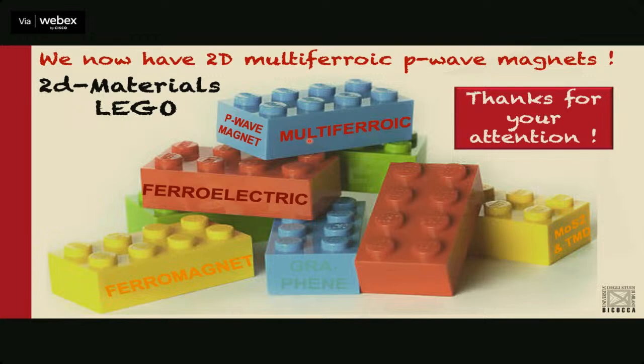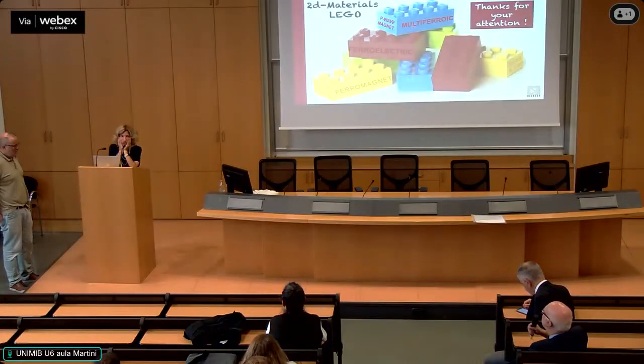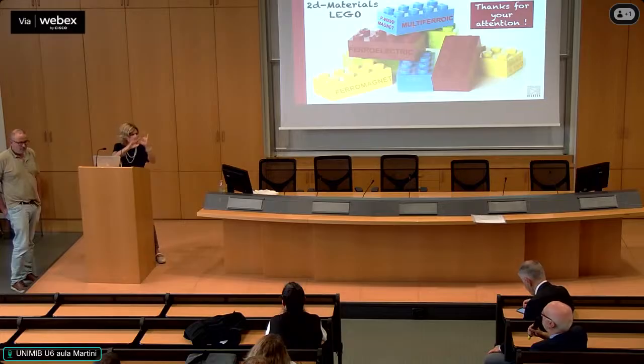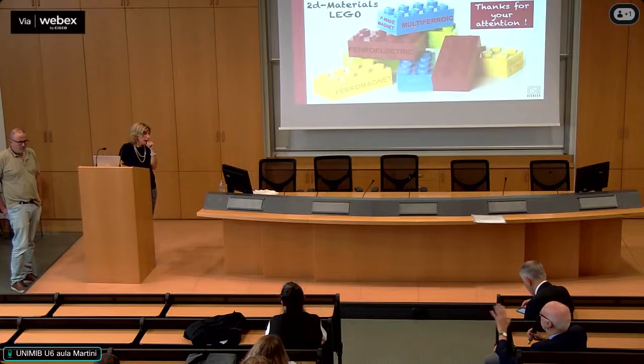Okay, so how would you do that? Let's say that ferroelectricity is a cooperative phenomenon, right? So once I create a displacement in this cation, then this one will also be affected. I don't know how to simulate the total energy of just one octahedron. With DFT you can do that if you have a relatively large supercell. Okay, so you would take a supercell of centrosymmetric octahedra, and then you would just displace one, in the center. Exactly.